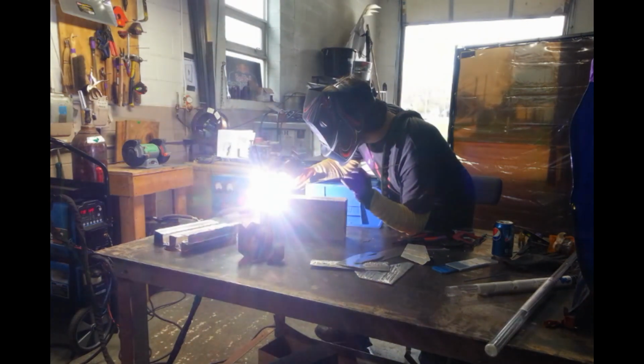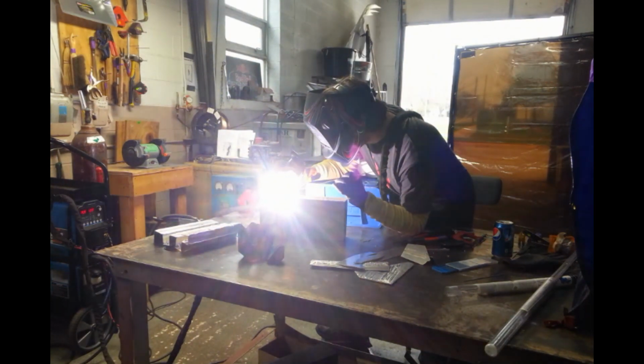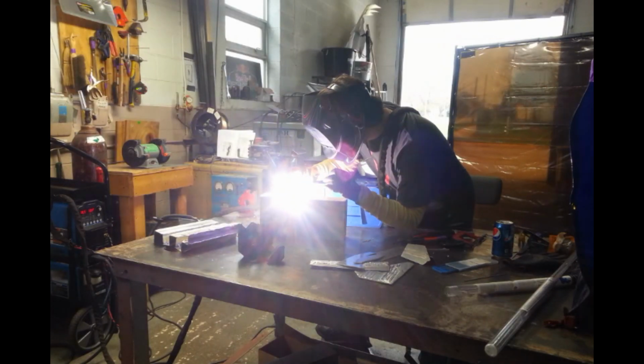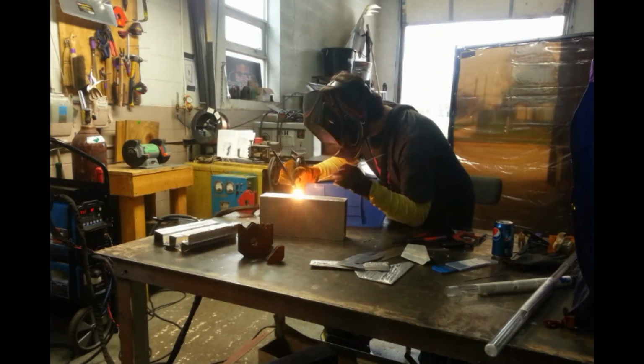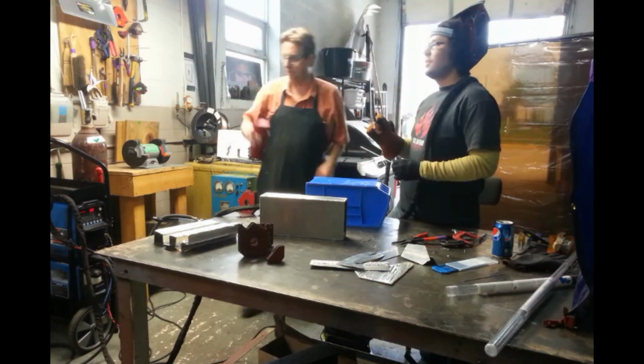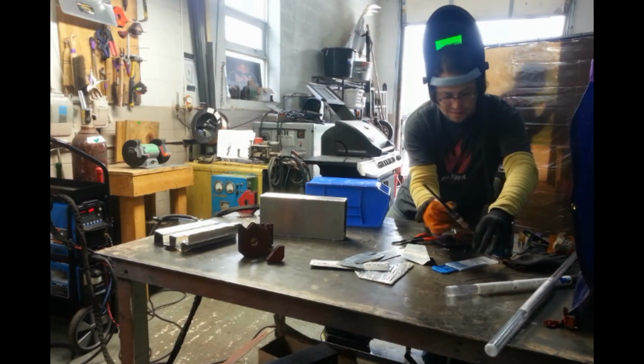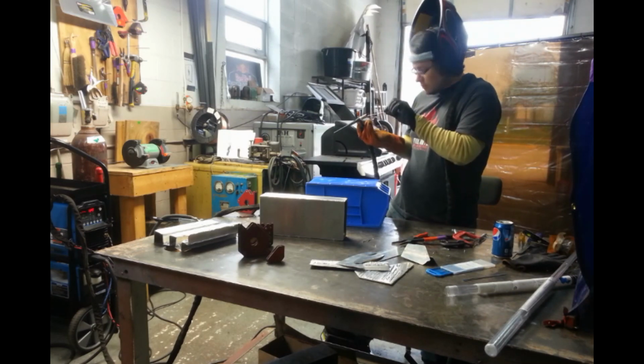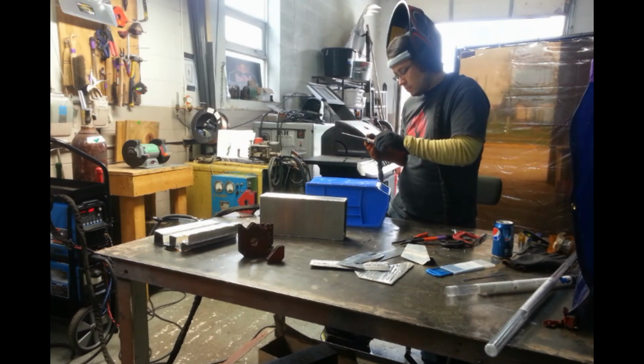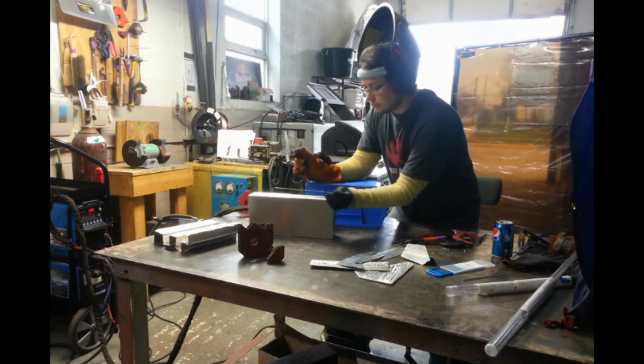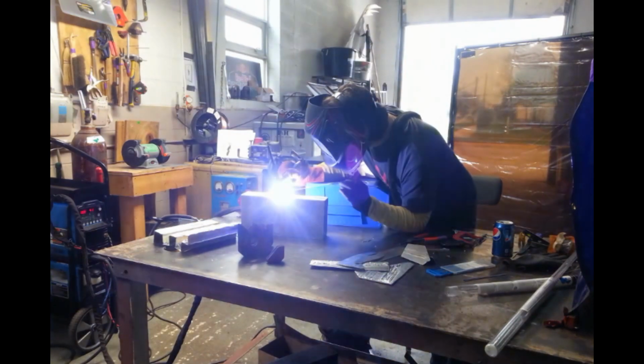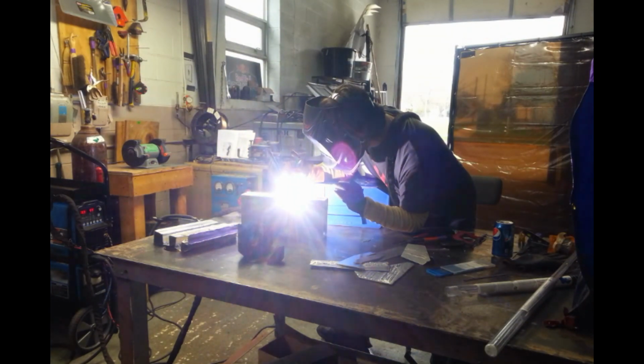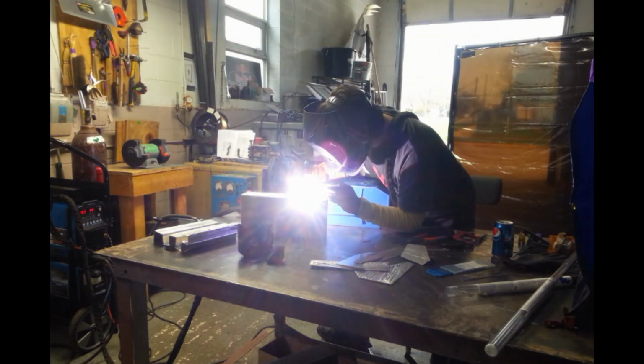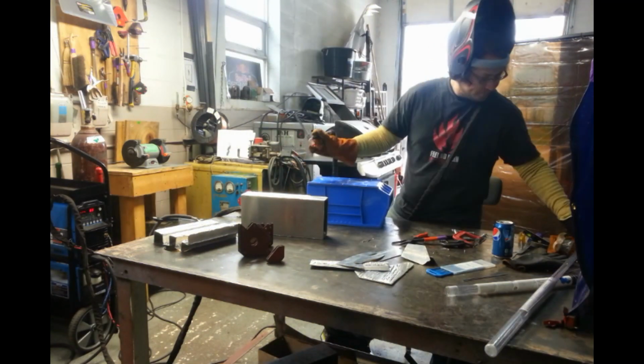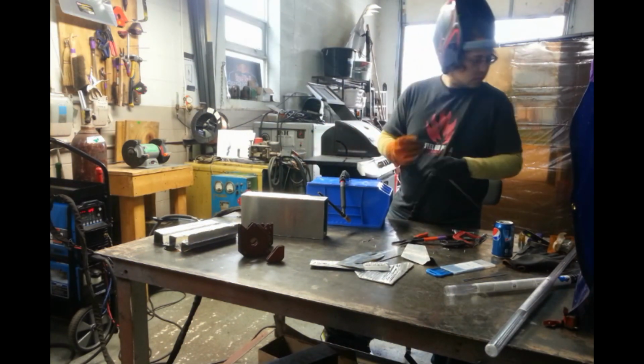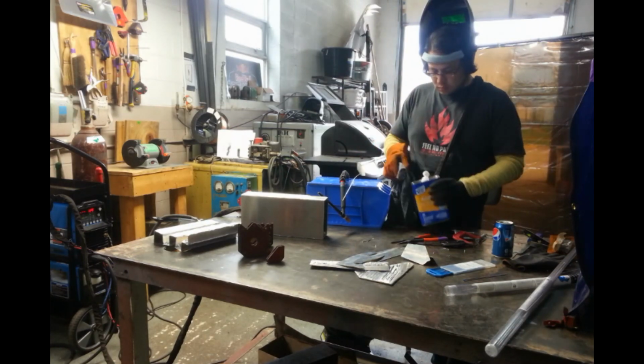So what I found, the settings I'm using are, I'm thinking about 120 amps, running 63 cleaning on the balance, as well as 160 hertz. So I was having some trouble with the material not being clean. I have a stainless brush, and I am using acetone as well, but it seemed like I was having problems until I turned that cleaning action. So that doesn't help the electrode as well. So I'm putting a lot of heat into that electrode.